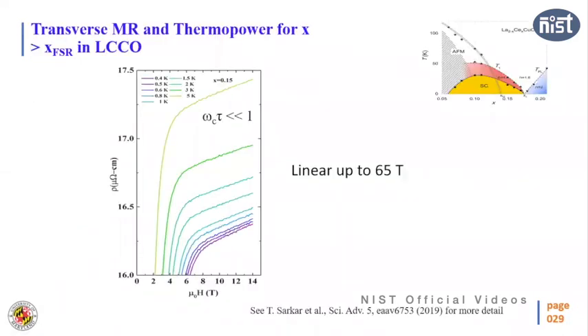It has also other strange behavior. Beside this linear in T resistivity down to 0 temperature, we measure the magnetoresistance of this material. Up to 65 Tesla, we found this magnetoresistance is also linear. So basically this line goes all the way to 65 Tesla, which is linear, but that should not be the case. In the low field means omega c tau is very, very less than 1. This should be quadratic. So it should show some kind of H square behavior. But it doesn't do that. It shows linear behavior all the way up to 65 Tesla.